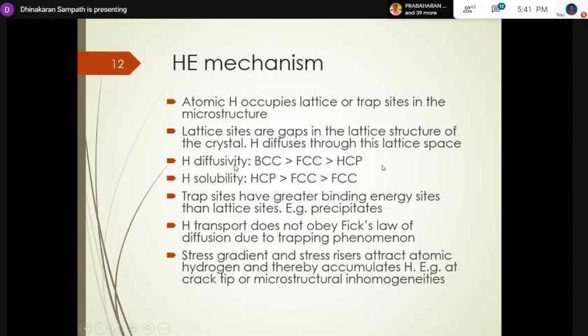So before that, hydrogen diffusivity, which is measured in centimeters squared per second. The diffusivity is the rate at which the hydrogen passes through the material. In BCC, body-centered cubic, it is very high compared to HCP. In the case of hydrogen solubility, that means how much hydrogen it can hold in the matrix, in HCP it is very high. In HCP, like zirconium and some forms of titanium, it forms hydrides, which is also very problematic. But today we are going to look at only BCC and FCC materials, like BCC steels and FCC nickel alloys, which are austenitic.